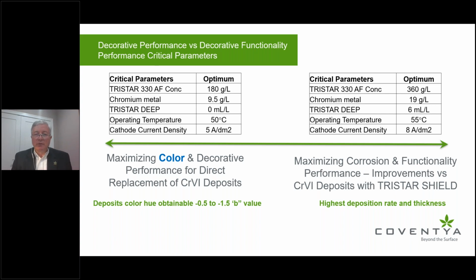We also, for the functionality applications, want faster deposition rates. We want to build a higher thickness and a quicker rate. So that affects color, having the higher thickness. It's less blue, but of course you get the higher corrosion performance. So we've balanced the system to be able to meet both.